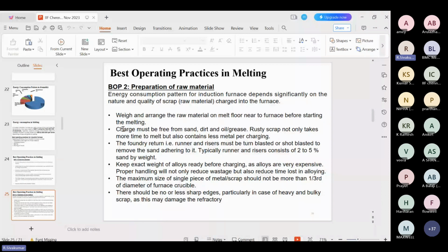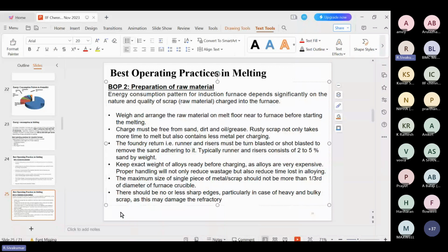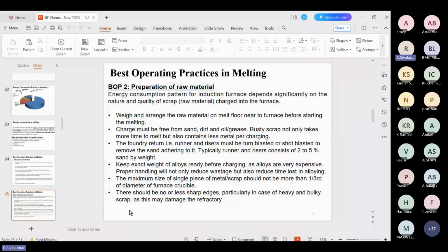Keep the exact weight of alloys ready before charging, as the alloys are very expensive. This practice is to be followed, and proper handling will not only reduce wastage but also reduce the time lost in alloying. The maximum size of a single piece of metal scrap should not be more than 1/3 of the diameter of the furnace crucible. All the OEMs specifically tell the foundrymen this during installation. So whatever the crucible size, the scrap pieces should be less than 1/3 of the diameter, so the scrap is to be broken and put in the crucible. There should not be sharp edges, practically in the case of heavy and bulky scrap, as this may damage the refractory. So this care is to be taken before pouring the metal into the crucible. Any sharp edges mean you have to charge the metal into the crucible carefully.